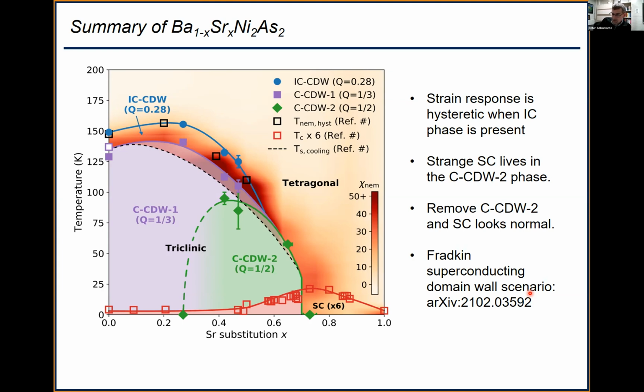If we go back with high resolution, there are materials like titanium diselenide where in the superconducting state the CDW actually becomes incommensurate because periodic domain walls form. This stuff happens in the dichalcogenides. It's known. So what we need to do is go and measure that at high resolution and see if the peak is split or shifted. That would tell you that the domain walls were ordered, and then it really would be some PDW or FFLO kind of phase. I can't tell you that doesn't happen, and it's known to happen in other materials.